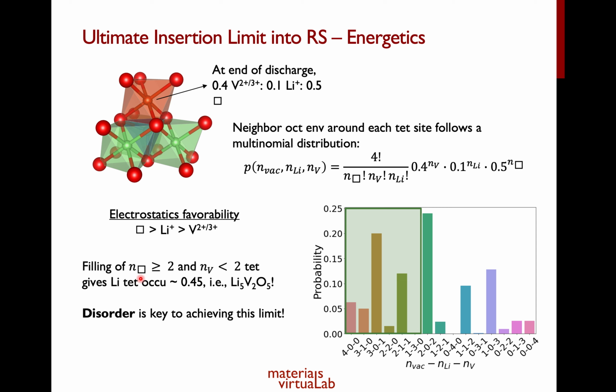And what we found was that if you occupy all the sites which have 2 or more vacancies and less than 2 vanadium, essentially what you achieve is a lithium tetrahedral occupancy of about 0.45, and that is exactly the lithiation limit that we have achieved experimentally, okay? Now, the other thing to understand is that disorder is actually key to achieving this limit, okay? So if you have a nice ordered rock salt, it no longer follows this multinomial distribution around each tetrahedral site, and the number of tetrahedral sites that you can occupy actually decreases, okay?